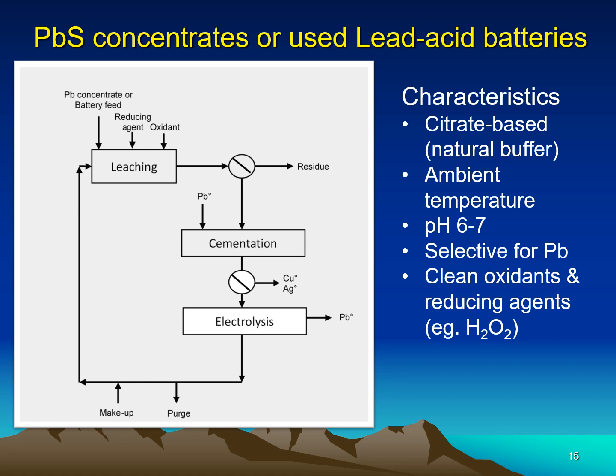It uses clean oxidants and reducing reagents. And what are the challenges? Well, the sulfate removal is a challenge, and the treatment of the purge solution should be very small. The amount of purge, and how we treat that and remove the sulfate to recover the citrate and the water, that is a challenge. And the operating temperature cannot be more than 40 degrees, because at that temperature the citrate decomposes.